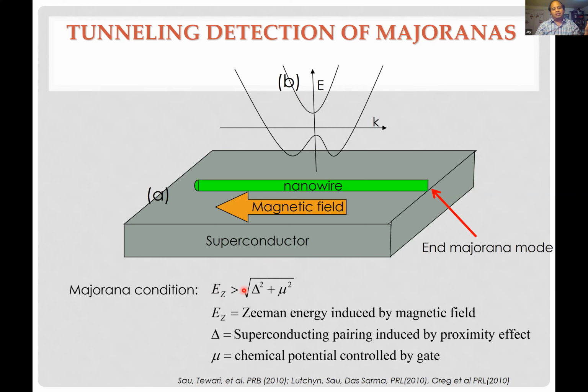But when it's bigger than the square root of delta squared plus mu squared, this is just some analytic formula, we would get an end Majorana mode. This Majorana mode has zero energy, so when we tunnel, we would see a zero bias peak. Okay, so this was our prediction, and indeed, the magnetic field had to be greater than the critical magnetic field.